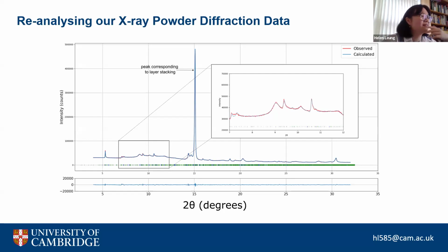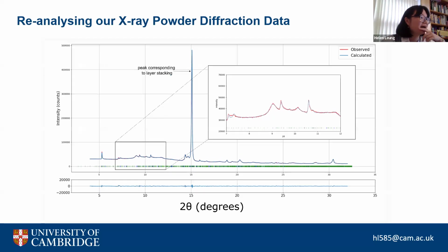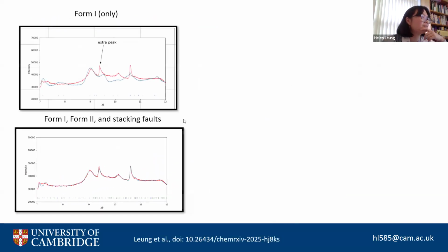And you can see here that this X-ray fit is now a lot better. We reanalyzed the same data that we had before with just form 1, and the fit is substantially better. And just to compare the fits from before and after, above is our form 1 with only our form 1 model, and below the fit is with form 1, form 2, and this supercell stacking fault approach.